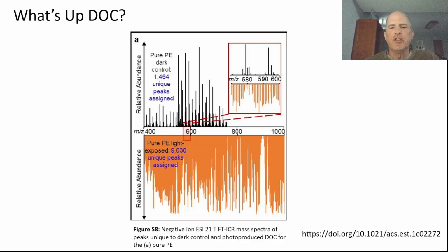Okay, so this is actually from a little different paper where the focus of this paper was more to characterize what the dissolved organic carbon is. But I wanted to show this to you. So this is a mass spec experiment. So the x-axis here is molecular weight. The black stuff that goes above the line is what was produced when they did it in the dark, so just sort of thermal treatment. And then the orange peaks below are what was produced when they used light treatment.